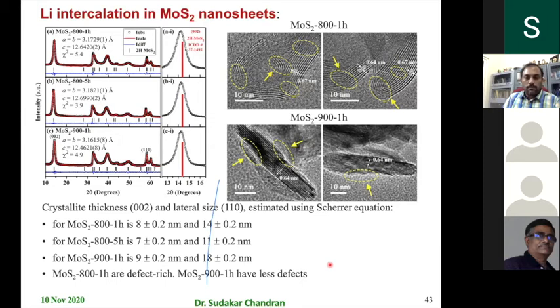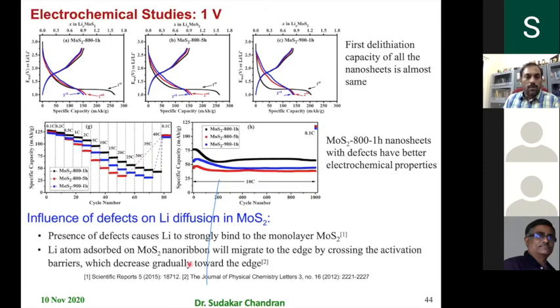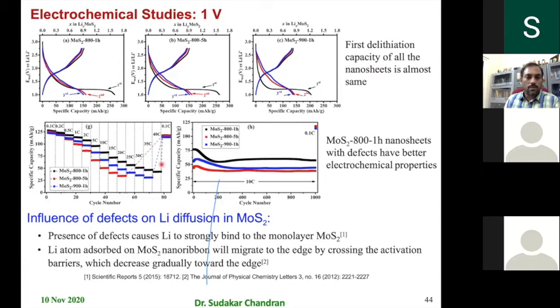Okay, so this I already mentioned, so let me skip this. In what way it does is, if you do the cyclic capacity measurements, some of these measurements, as you can see, are at high C rate, 25 C, 30 C. So it can work at very high C rate, still giving high specific capacity.